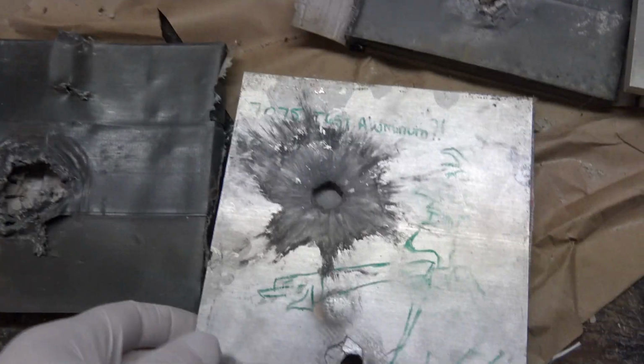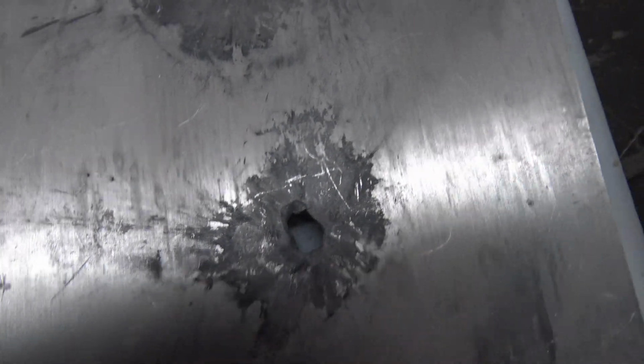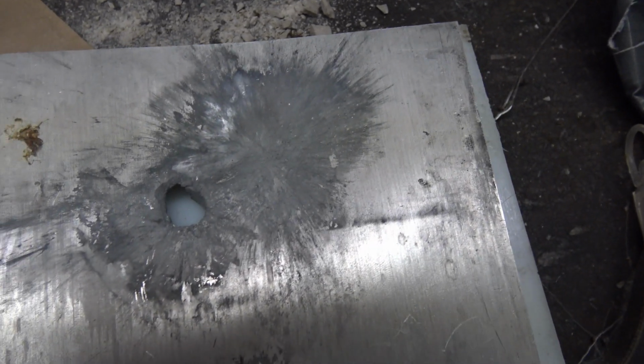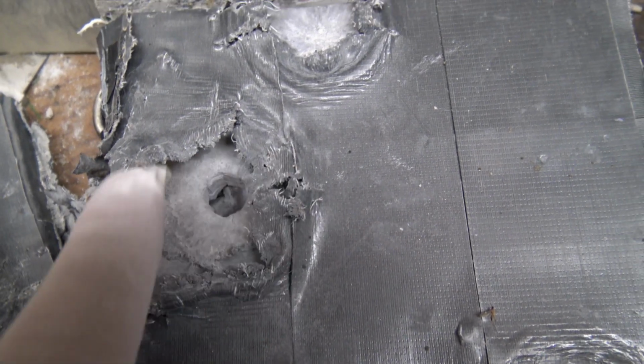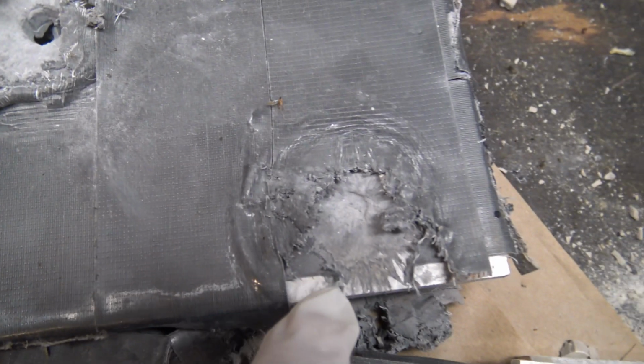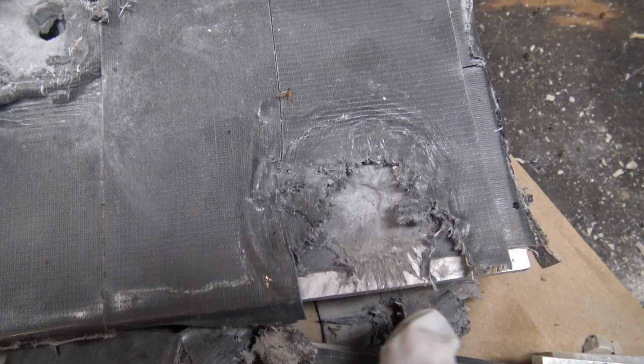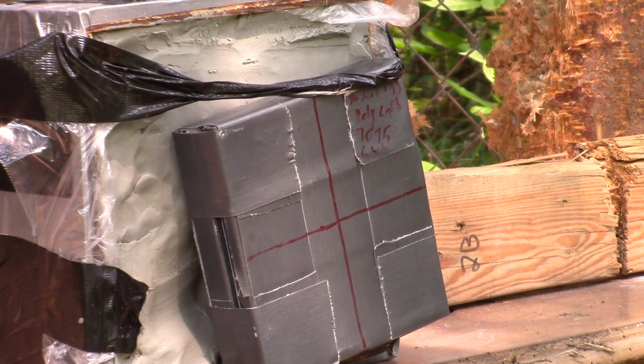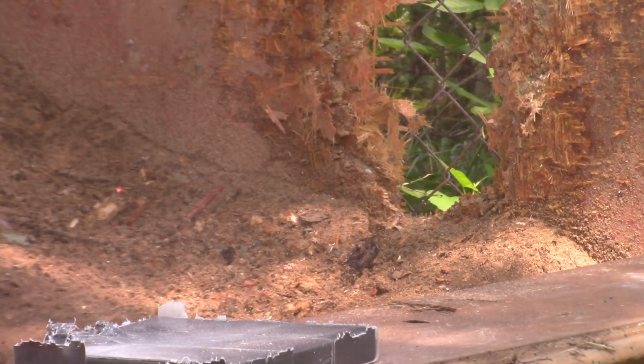There also was major spalling between the porcelain and the 7075. I noticed this more and more as I was taking the plates apart later. This often caused the plates to blow apart, even though I would add more duct tape to keep them together between subsequent shots. This left large areas of lead and jacket sprayed over the surface of the 7075, indicating that the bullet was disintegrating between the porcelain and the aluminum.